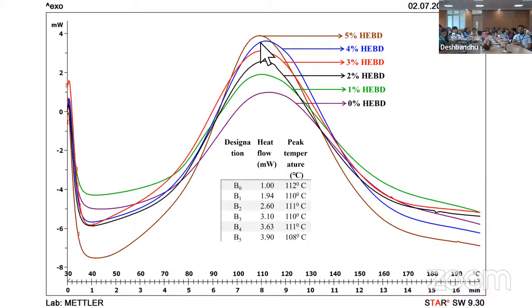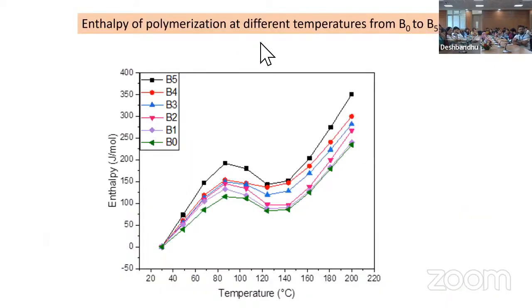However, the peak temperature is also shifting to a lower value, from 112 to 108. Enthalpy of polymerization at different temperatures is plotted here. This is again showing the same trend, that enthalpy of polymerization is increasing while we are increasing the concentration of this monomer.